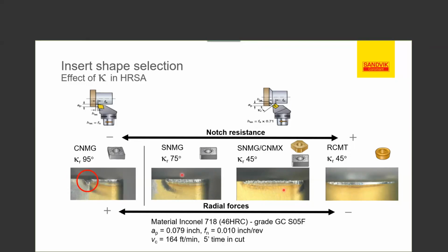All these inserts here are run at the same criteria: 80 thou depth of cut, 10 thou feed, 160 surface feet, all for about 5 minutes. And all we did was change the entry angle of those inserts. You could see this from a notch wear all the way to a 45-degree style entry angle. You can see the process security you're now going to have. Again, if you're going up against a shoulder, it's a necessity to use a CNMG style insert as opposed to the others, but just be mindful of the challenges you're going to have.